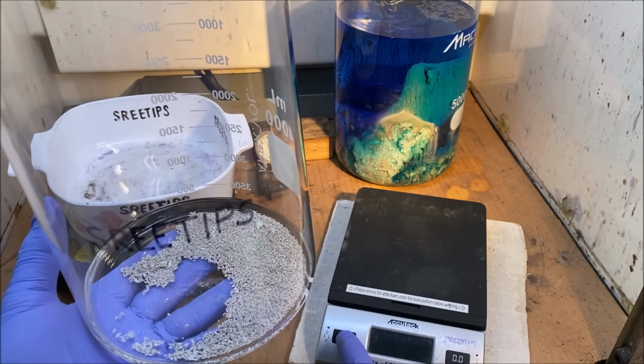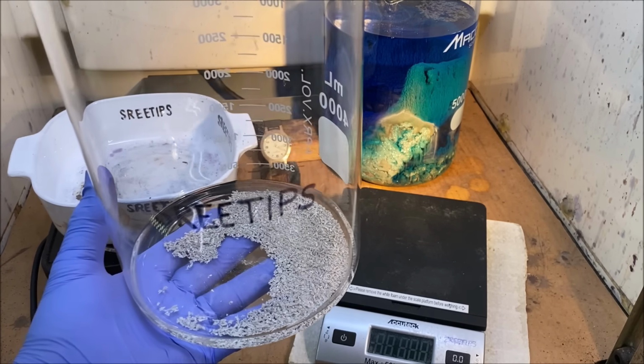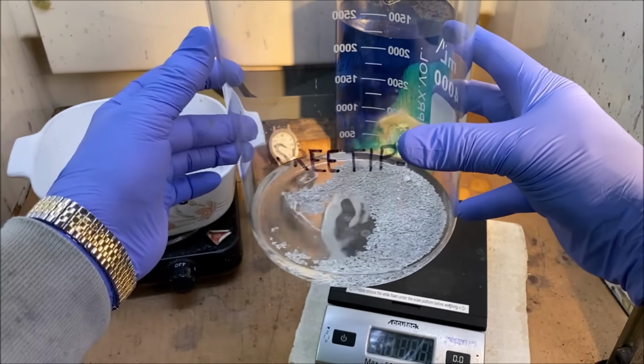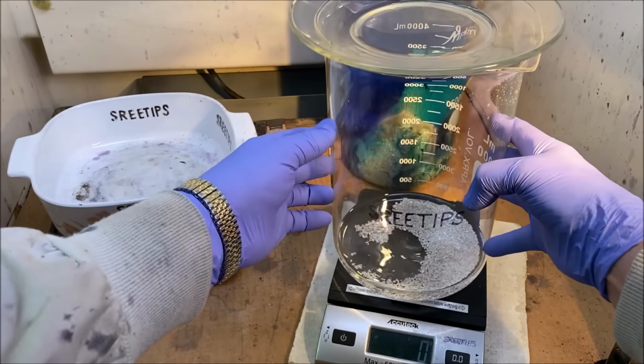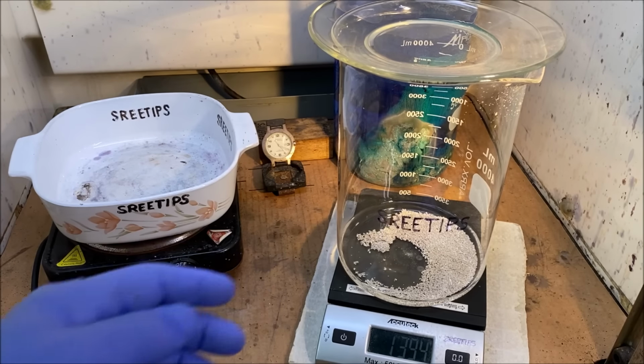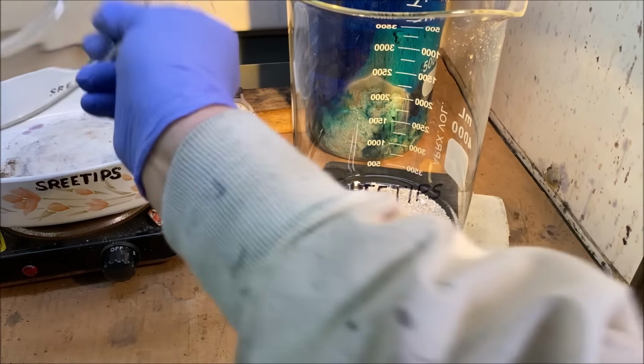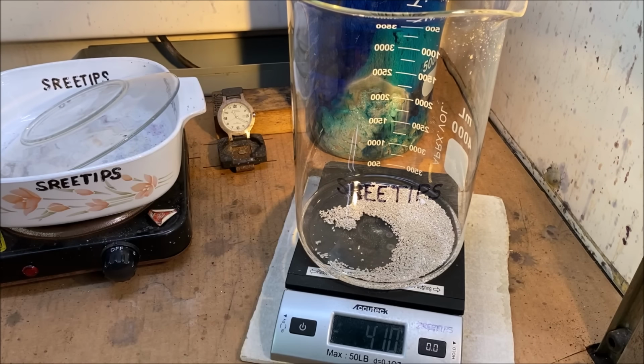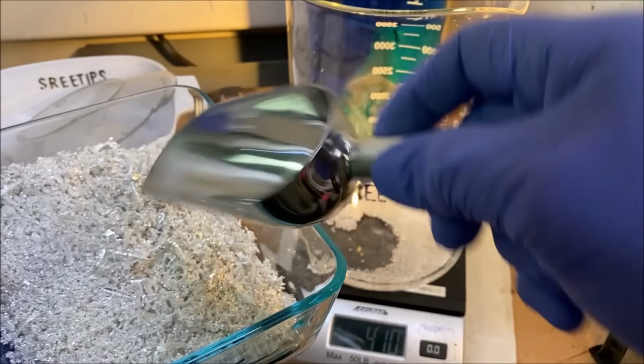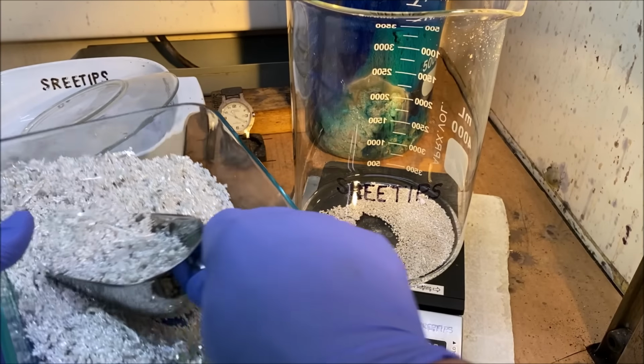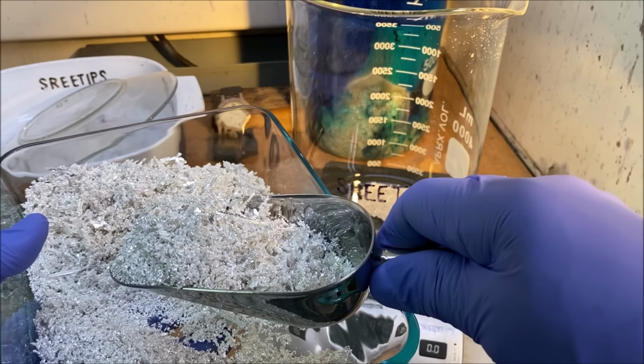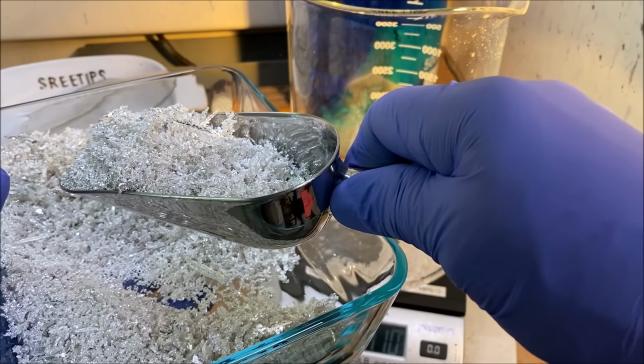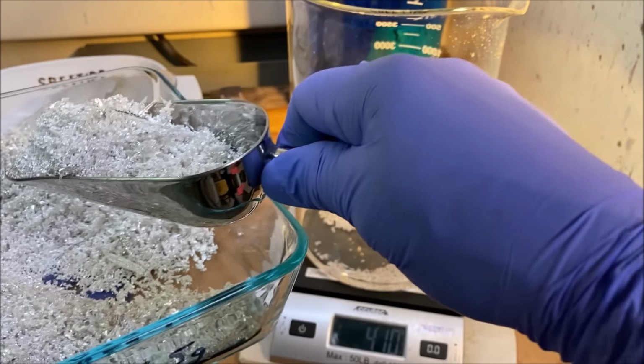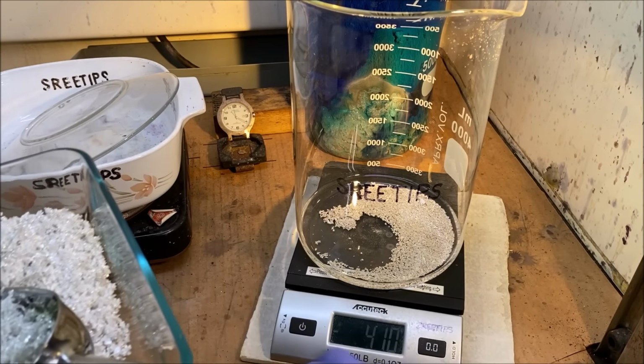Sreetips here, and today we're going to fire up the Beast, which is my 6-liter silver cell. For the 6-liter cell, I use about 1,000 grams of pure silver to create an electrolyte that's about 150 grams per liter of silver. So we're going to measure out 1,000 grams here.